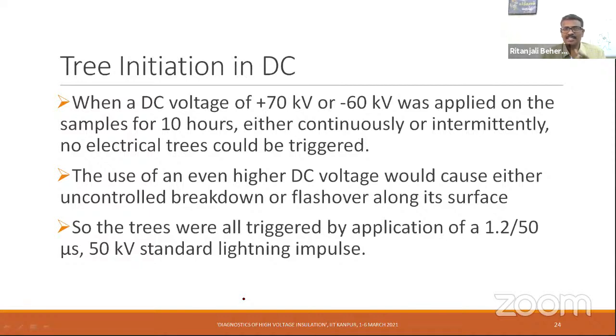However, in the case of AC, it was not so. Even at much lower field, we have seen the tree has been initiated. Obviously, the reason could be the constant injection of electrons, and at the same time retrieval takes place. So at the tip, one thing is the highly divergent field, and second, the heat formation. All these things lead to very quick formation of the first branch of the tree.